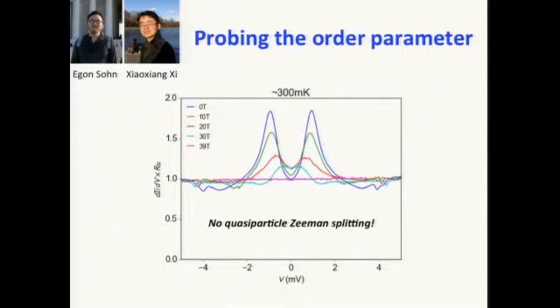This is the experimental result we've measured at 300 millikelvin and under different magnetic fields. You can see under zero magnetic field, there are two spikes corresponding to the divergent density of states. The differential conductance does not drop to zero here because of Andreev reflection, which I'm not going to go into the details of. This is actually a point contact device rather than a tunnel junction device.